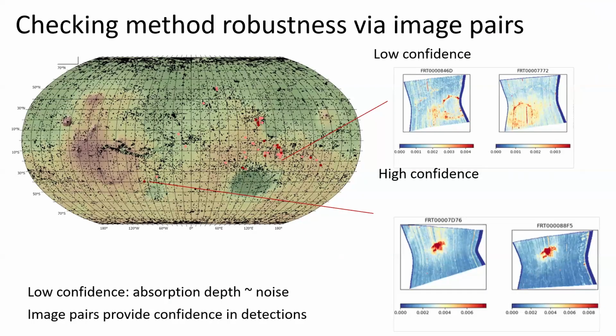Some of the images with prehnite detections have overlapping CRISM images, and this gives us the opportunity to check how well our algorithm is working. On the top right, you see two images which we identified as low confidence, and on the lower right, overlapping images where we have a high confidence of prehnite detections. The color indicates the depth values of a feature around 1.48 micrometers. And you can see that with high confidence, the higher, warmer-colored areas overlap very well.